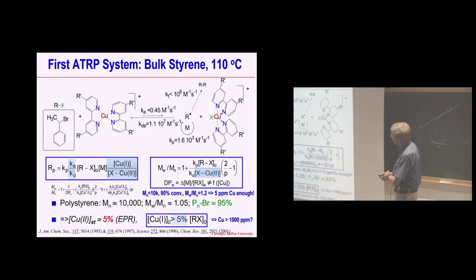So it happens that this alkyl halide will approach the copper complex, and in transition state, this bromine will bridge between carbon and copper, and eventually will oxidize copper 1 to copper 2 and form a radical. This radical can be involved in 3 different reactions. Radicals can obviously terminate, they can propagate, and every act of termination will accumulate this persistent radical. So we'll have a higher and higher concentration of this copper 2, and then this radical, instead of termination, will have a cross termination, taking this halogen atom, converting back to a dormant state.